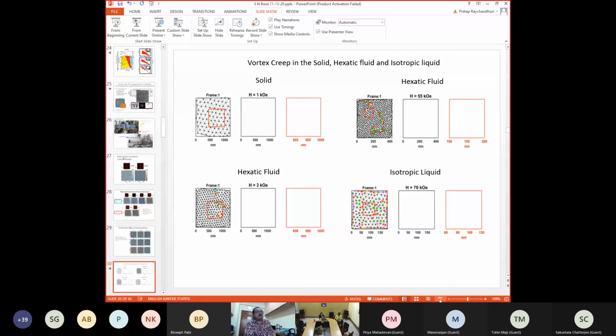When you keep on tracking these vortices, you see that when it's a solid, you just have very small motion of the vortices around their main position. Then when you go to the hexatic, it starts flowing. But in the hexatic, it flows along preferential directions. Look at, for example, this image here. These lines are the trajectory of each vortex that is being shown.